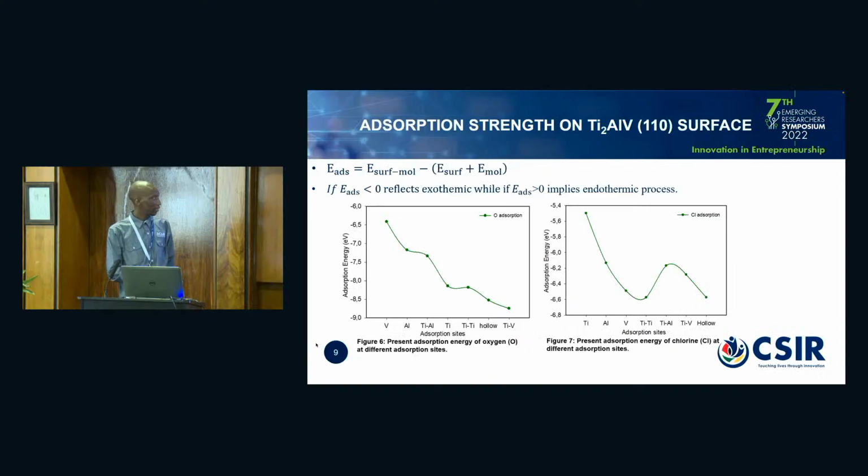Then let's check which surface site was more reactive in this case. We see that, looking at the magnitude of the adsorption energy, the hollow site and the titanium vanadium bridge site are the most reactive sites on these surfaces.